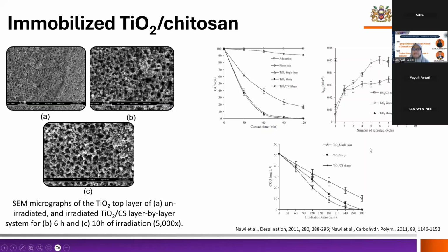The photocatalysts have also shown a good mineralization performance, which is measured via COD analysis. We observed that the TiO2 chitosan bilayer has a very good mineralization rate. So this work has been published in 2 articles.